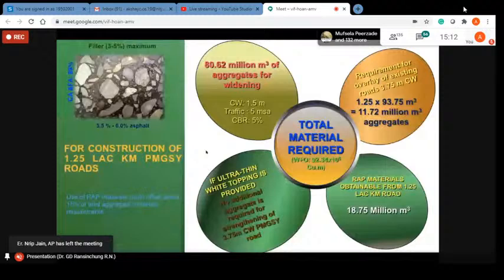And for your kind information, especially for the UG and PG students who are not well versed with rigid pavement construction, the DLC mix shall not be designed following Abrams' law. That means we are not going to follow the water cement ratio while formulating the DLC mix. We rather go by the compaction methods, the standard Proctor tests. So we have conducted the standard Proctor test, and we have mapped the OMC and MDD for the different RAP material incorporation levels, and then tried to find the best possible